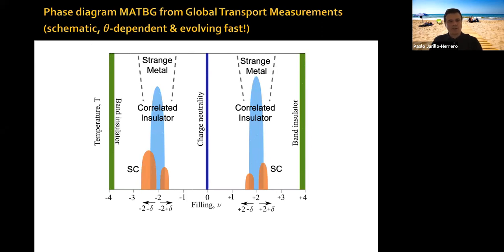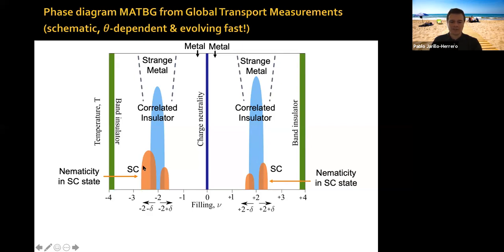Later, we and others saw that there is this linear in temperature resistivity behavior. It is primarily present around the correlated insulator states. And this is very reminiscent of the strange metal behavior in correlated materials. Whereas if you go, for example, near charge neutrality, you have regular metallic behavior. The resistivity is not linear, it's approximately quadratic in temperature. You also have this superconducting state that is anisotropic. It exhibits anisotropies, which have led us to the conclusion that there is nematicity in the superconducting state of magic angle graphene. You also have competition between different orders close to these integer filling factors, particularly close to minus two. And you have also nematicity anisotropies in the normal state of the superconducting state.